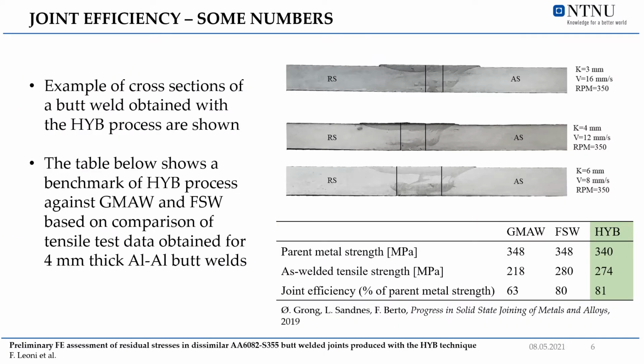In this slide, examples of cross-sections of a butt weld obtained with the HYB process are reported. The butt welds were obtained for different groove widths between the plates, showing how the technique can be well suited for different needs. In fact, one advantage against friction stir welding is the possibility to have a gap between the materials to be joined without undergoing problems of lack of filling.